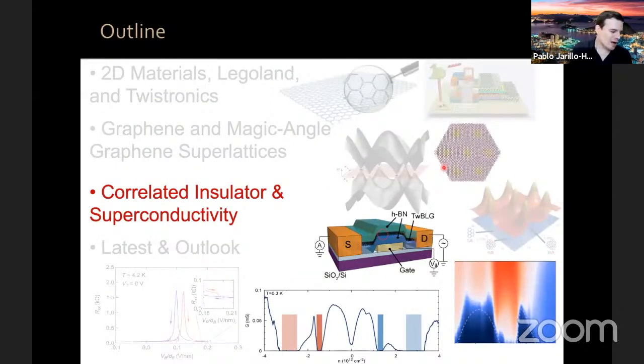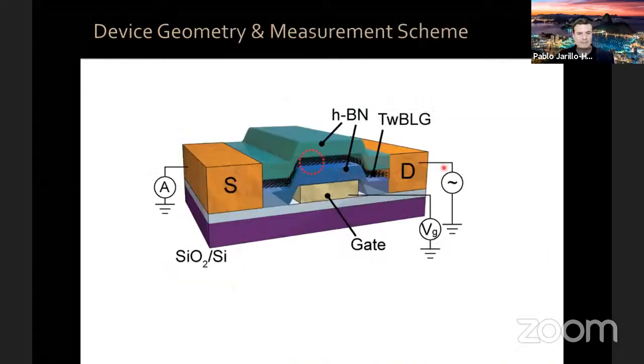Now, let me tell you about our experiments and our data. This is the device geometry and the measurement scheme. We fabricate these devices where you have this twisted bilayer graphene, which is encapsulated between top and bottom hexagonal boron nitride. This is a very high quality dielectric. The twisted bilayer graphene is contacted by source and drain electrodes so that we can apply a voltage and measure current. And then we have a metallic electrode, a gate, parallel with the twisted bilayer graphene so that we have a field effect transistor geometry. And by applying a voltage to this gate, we can vary the charge density in the twisted bilayer graphene.